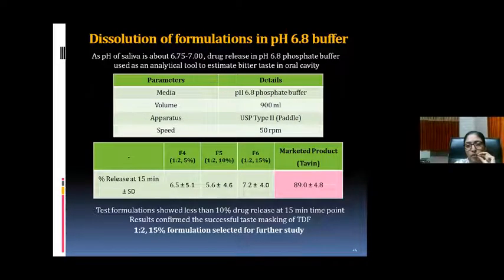Similarly, the studies were carried out in pH 6.8 phosphate buffer. Now, why is 6.8 phosphate buffer used? Because the pH of saliva is about 6.75 to 7, and drug release in pH 6.8 phosphate buffer is generally preferred as the analytical tool for estimation of the bitter taste in the oral cavity.